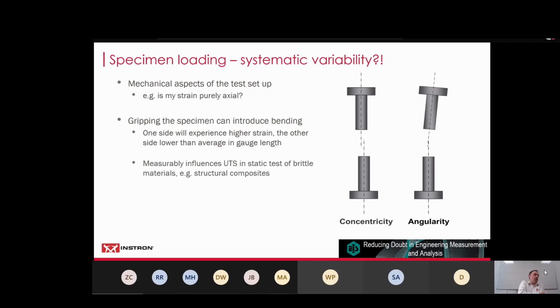Now, if it's something all very ductile and a great big specimen doing just a very basic tensile test, it probably won't make any measurable difference. Probably, mind you. However, it's been shown for many, many years that you can measurably influence the tensile strength just in a static test if you have a very brittle, stiff material, something like a heavily fibre-reinforced composite. And similarly, if you're looking at fatigue testing or cyclic loading, then if you have a higher tensile stress on one side or at one point, you will accelerate the crack initiation. And if you accelerate crack initiation, then you're going to take something at least off of the total fatigue life.